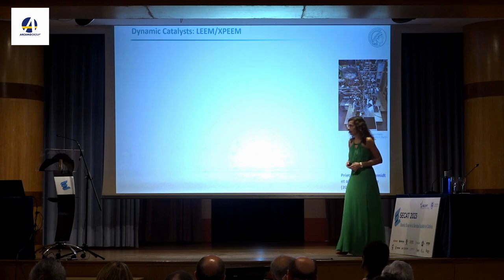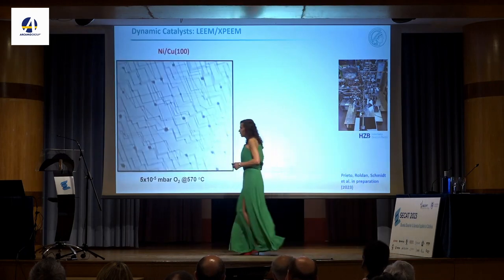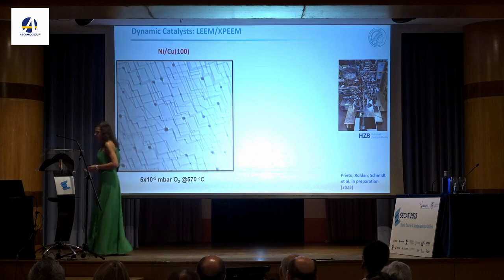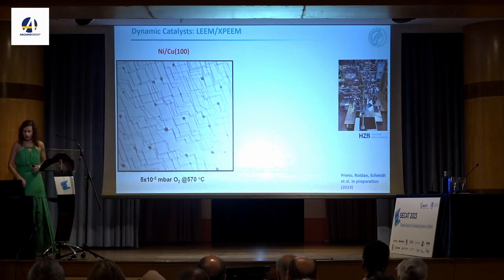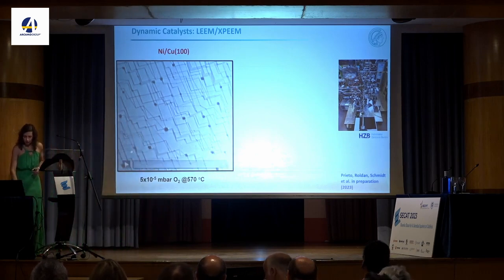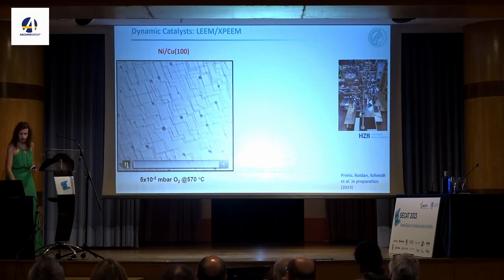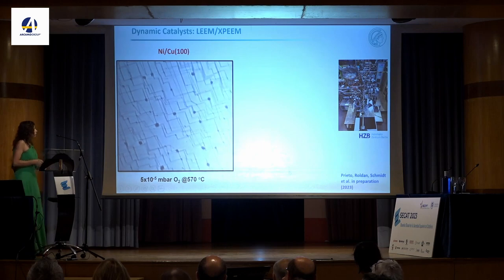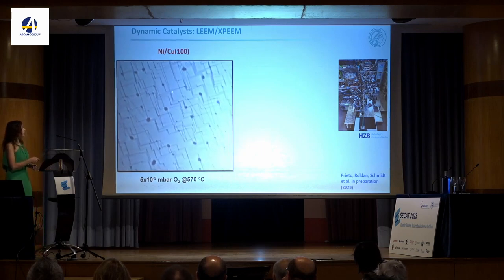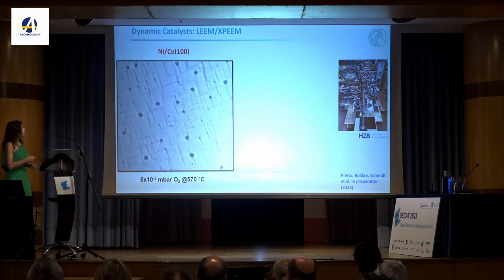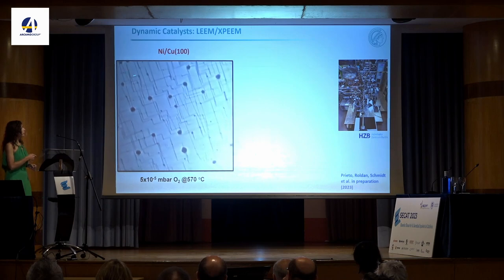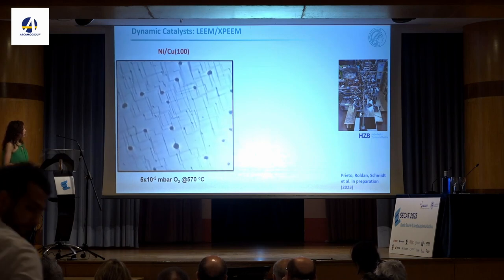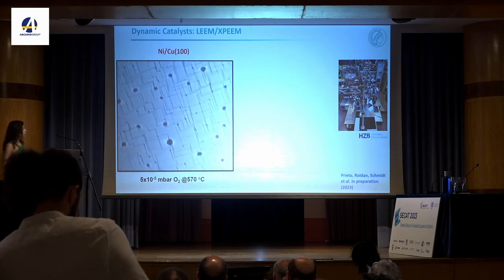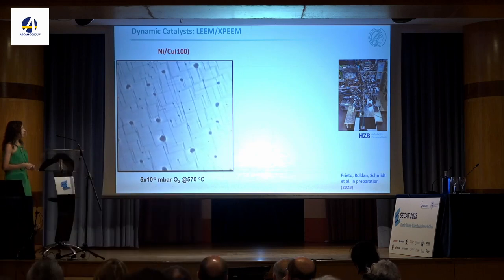So catalysts are dynamic, and I wanted to give you some illustration about how complicated things are, even when you start working with a model system. So think about a single crystal. This is a copper single crystal, and you're going to see here, what you see moving around, these are steps. So here in black, these are nickel particles. And this sample is exposed to oxygen at about 600 Celsius.